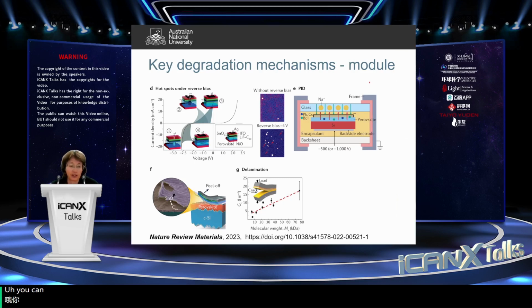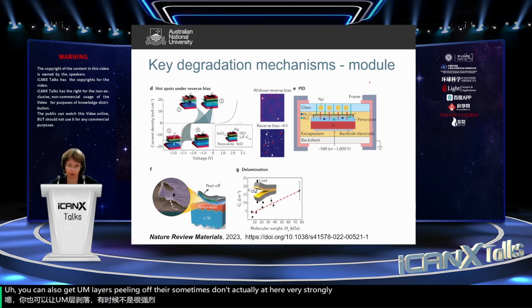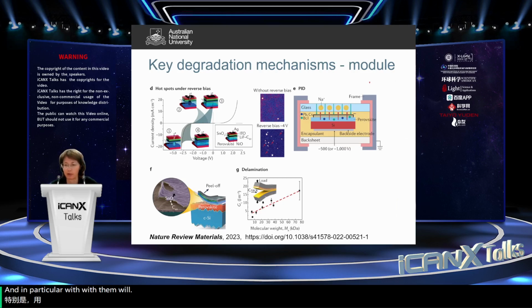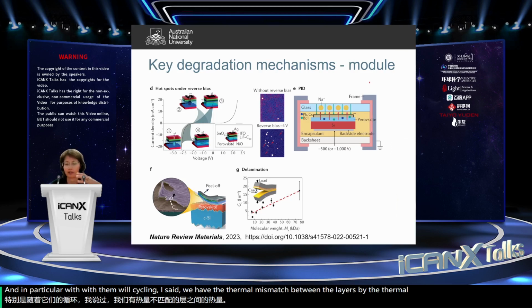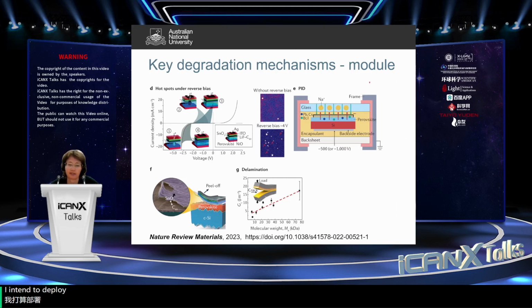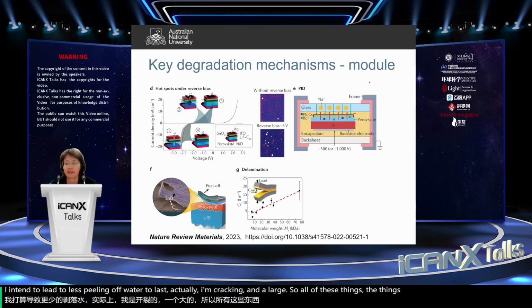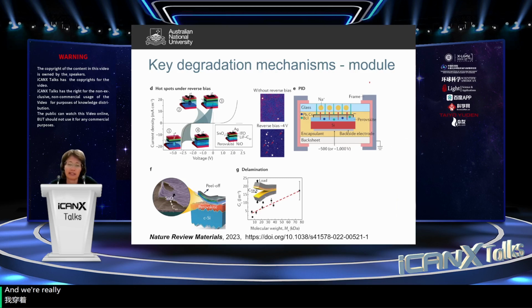You can also get layers peeling off. They sometimes don't actually adhere very strongly to the perovskite. And in particular with thermal cycling, I said we have the thermal mismatch between the layers. So the thermal cycling will tend to exacerbate that and tend to lead to layers peeling off or to layers actually cracking under load. So all of these things are things that we need to figure out, and we're really only in relatively early stages of doing that.